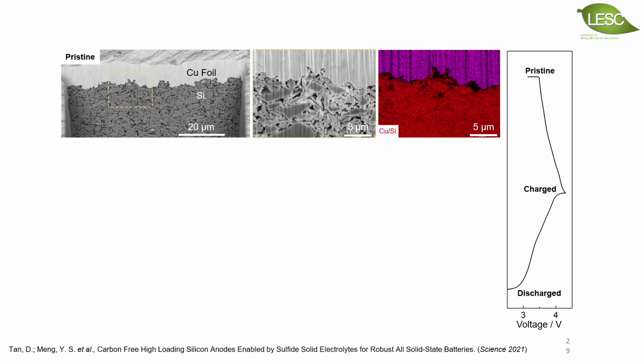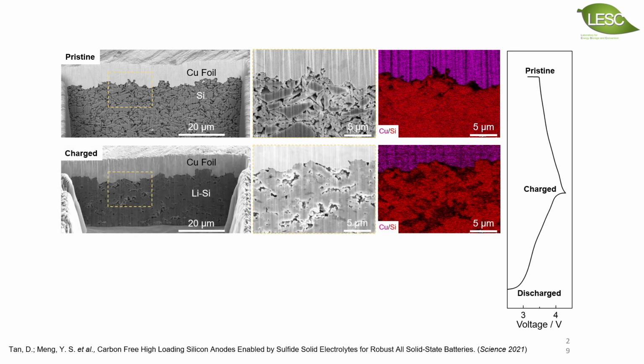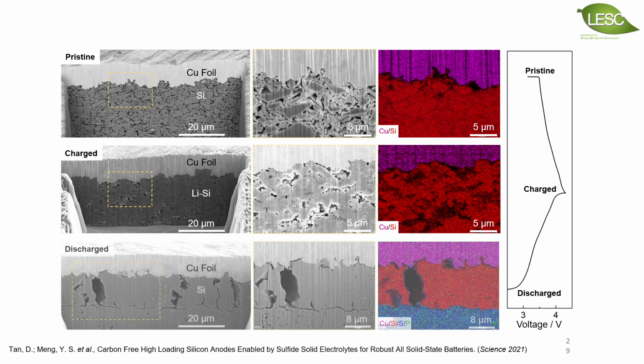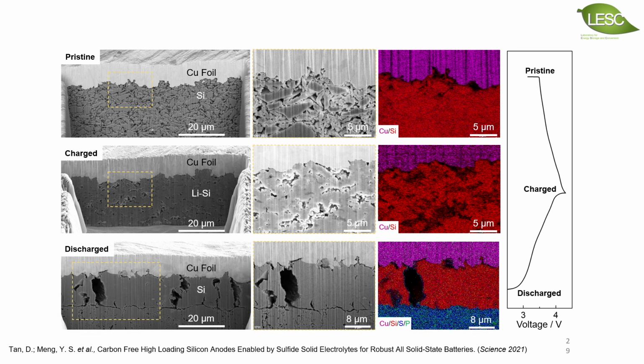And this process is visualized by cross-cutting SEM and the voltage curve. So you start with a very low-quality silicon, okay? There's a micron silicon where you can actually see a lot of voids. And when you lithiate, you drive the lithium in using electricity, you can see complete densification of this silicon, okay? Now, the magic happens, and until today, two years after the Science paper was published, we could not explain it: when you put the lithium back to the cathode, the pores completely redistribute, and we actually form this kind of columnar pore structure in the silicon, and the macro dimension of this silicon does not change.